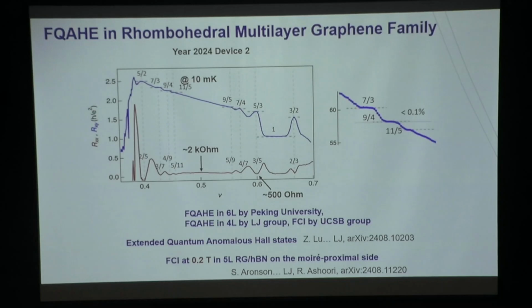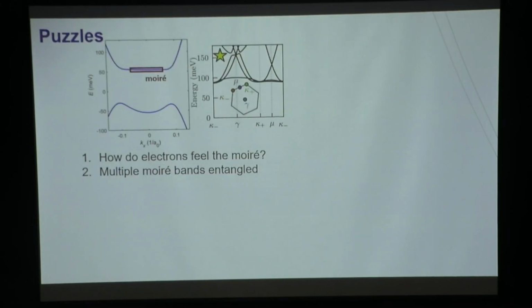So experimentally, it is satisfying that we observe this effect. However, I should tell you that we don't understand why and how we can get fractional quantum anomalous Hall effect here. You may get confused, right? Because I motivated this by telling you we should mimic Landau levels. Well, in reality, that just doesn't work here.